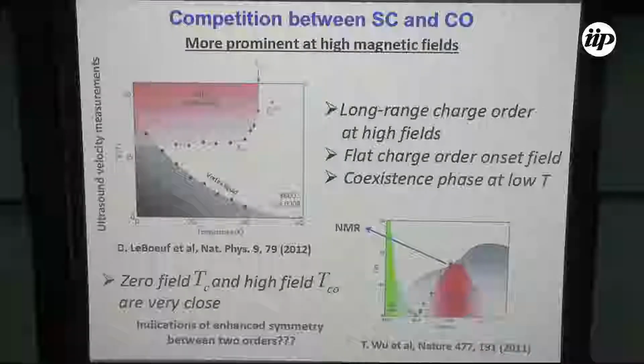is very close to the zero field superconducting TC. So this was also seen in NMR measurements. To be very specific, they looked at the TCO as a function of doping, and at 12%, they saw that this TCO is equal to TC, exactly.